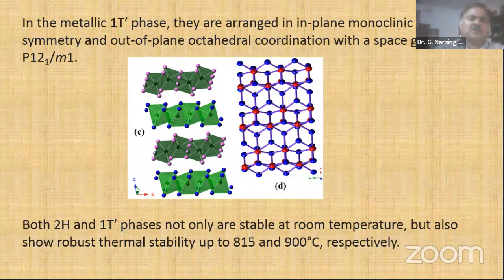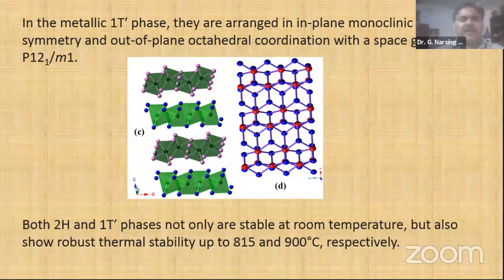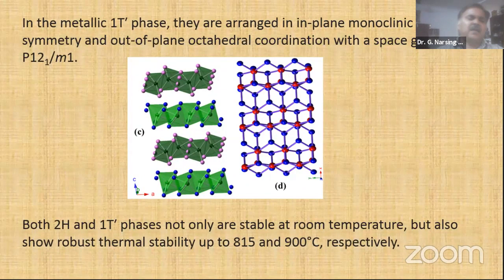So both 2H and 1T prime, that is hexagonal and monoclinic phases, are not only stable at room temperature, they will go up to 900 degrees centigrade without changing the phases. But at low temperature, 1T prime will change to 2H. So this is the stability as well as different types of properties that MoTe2, that is molybdenum ditelluride, will show.